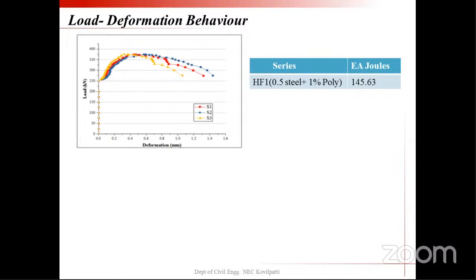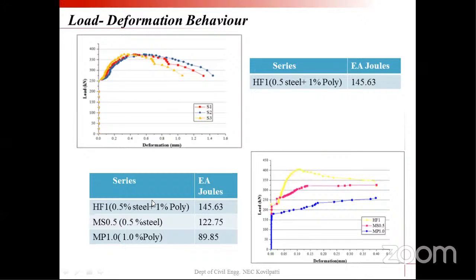Out of that, some specimens may behave till the end of the strain softening or strain hardening. Some may immediately fail due to some mechanical testing equipment issues. That is also one parameter. So we have to actually cast more specimens when making trials. So for HF1, the energy absorption is 145. And here you can see the comparison made with HF1, because it is made with a combination of 0.5 polyester, 0.5 steel and 1%. So the energy is improved from 120 to 145, and for MP1 polyester from 89 to 145.